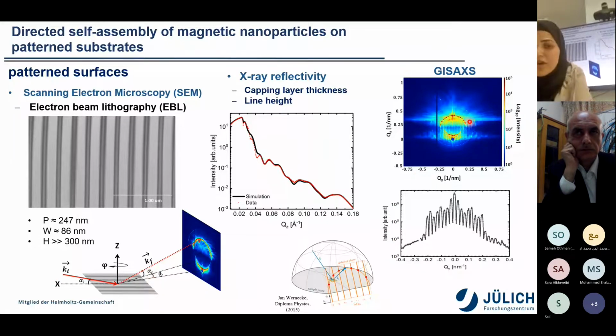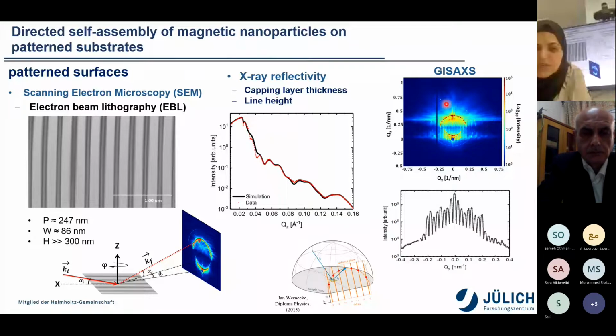We obtained further periodic orders, due to the periodic structure, and the diffuse lines, which come from the roughness of the lines or sidewall angles, and also from the stitching of the electron beam lithography machine. After integrating the intensity around the semicircle, we end up with this intensity integration, which shows only one fluctuation with two slopes.